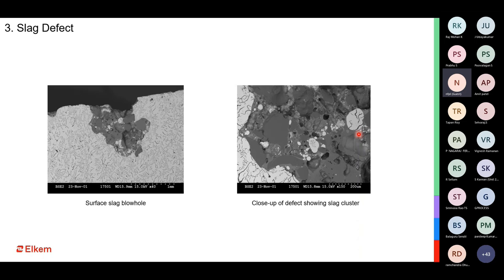The third defect is the slag defect, something which is very common. And we do find this kind of defect in foundries where we do not have either, one, a very good way of removing slag, or two, too many factors which are contributing to the generation of slag. This slag can be on the surface. This slag can also go along with the liquid metal inside the cavity of the casting. So it can cause an inclusion defect, that is slag, and sometimes this slag can also emit gases. So the slag defect, or the slag inclusion defect, in many cases also comes in combination with the gas related defects in the casting.